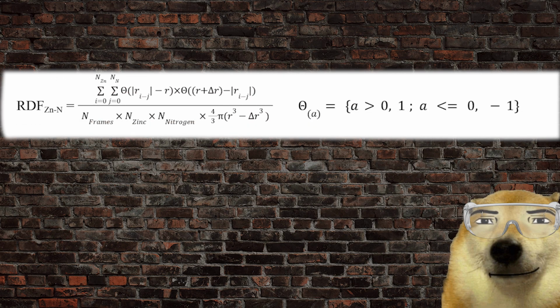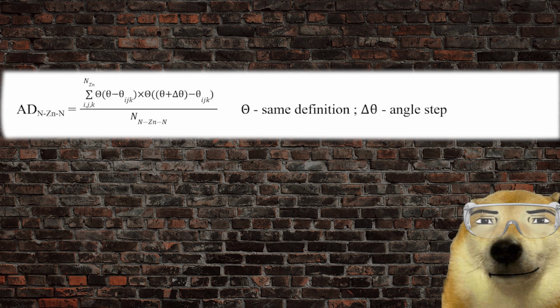Firstly, their RDF, radial distribution function of zinc nitrogen, which showed at what distances from the zinc was nitrogen the most likely to be found, how much of it and how it behaved at greater distances as the disorder in the system reaches roughly the ideal gas law. Also, their angle distribution of nitrogen-zinc-nitrogen complexes that display at what angle is the most probable for such structure to be in. Here, we look for higher peaks and lower dispersion.